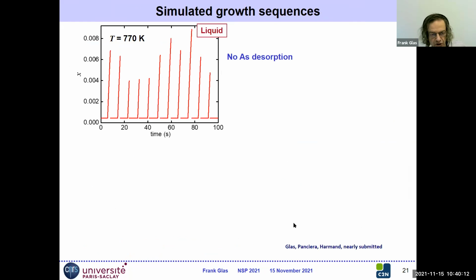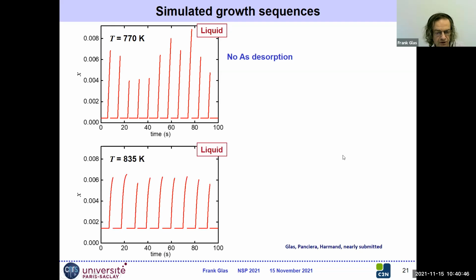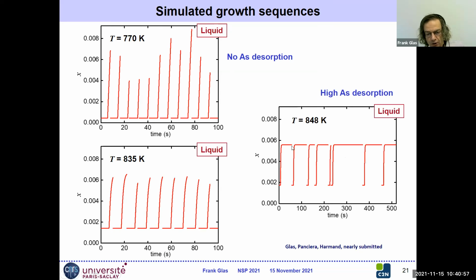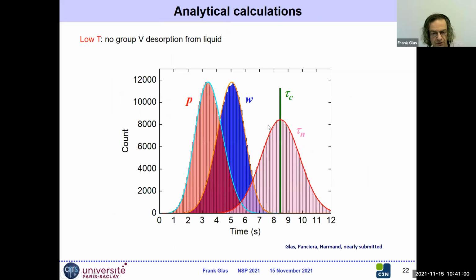And briefly, we have 3 regimes. At low temperature, I look here at the liquid. For a low edge energy, the liquid is at equilibrium with the solid during the waiting times. Then liquid concentration increases linearly up to nucleation. At nucleation, we form a partial monolayer. And then it stays at equilibrium during propagation. Then when the monolayer is completed, it increases again, new nucleation, and you see that nucleation can happen at various concentrations. If we increase the temperature, we have this non-linearity, which is a sign of the desorption. And at higher temperature, we have desorption and we can reach some kind of equilibrium. I'm not going to speak about this today.